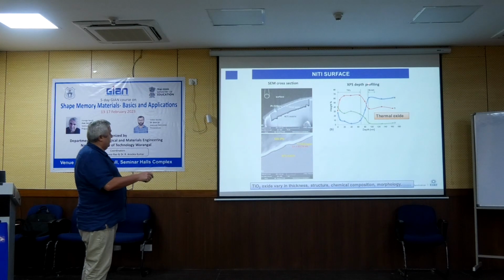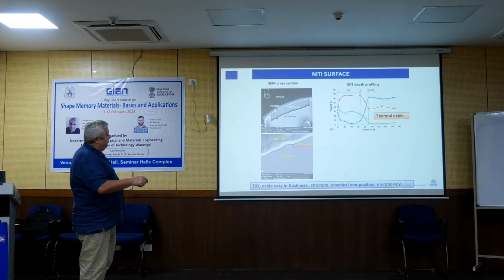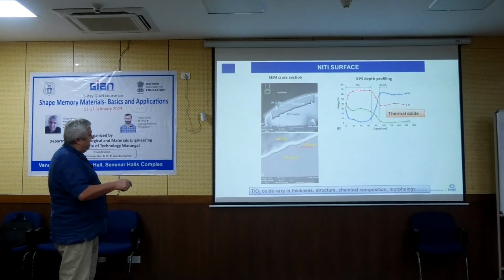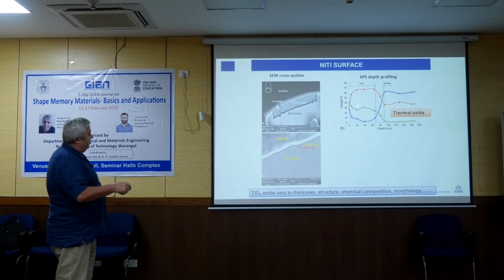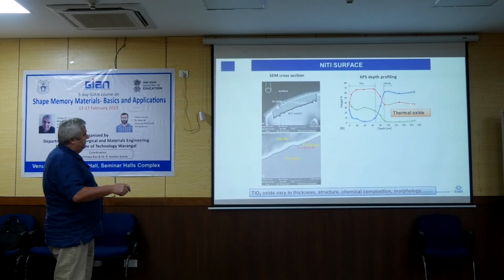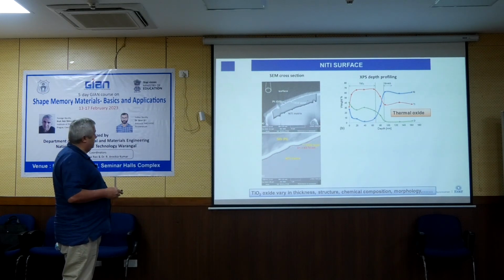This is some experiments with XPS depth profiling, showing what is the thickness of this nickel enriched layer. So nickel is the blue. So you see here something like a 20 nanometer thick layer which is enriched with nickel. The red is titanium oxide on the surface, so it is above the nickel enriched layer.